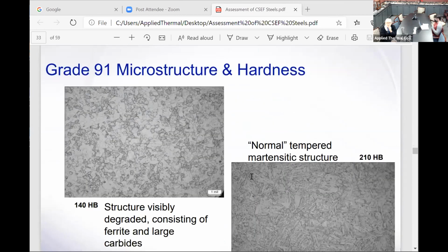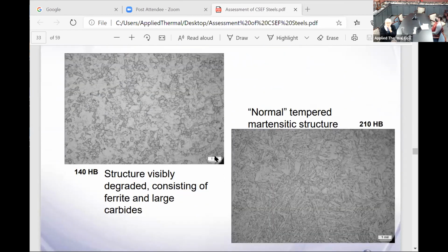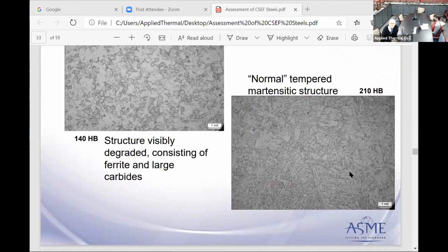Moving on here, this is showing again, Dr. Joey's showing quite a few of these, but this is showing material basically consisting of ferrite and large carbides. And you can see here it has pretty low hardness. Here's one with a pretty normal tempered martensite structure, and you're sitting there at 210 HB, which is where you want to be.